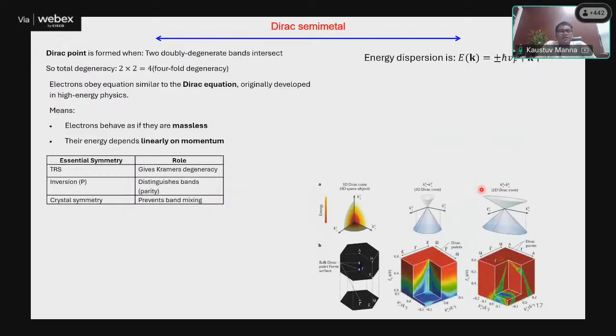Now we come to the next compound, the next level of challenge, where the surface state of this topological insulator, which was the band crossing, was the Dirac cone. The quasi-particle excitation of those charge carriers had a Dirac cone, but the bulk was gapped out. The bulk had a topological insulator state, and irrespective of band inversion, it was gapped out. It was an insulator state. Whereas in the Dirac semimetal case, we have the same quasi-particle excitation as the surface state of the topological insulator, like a Dirac cone, but now the same Dirac cone happens in the bulk, inside the material itself. Now the material is metallic in nature. It is not a gapped-out material.